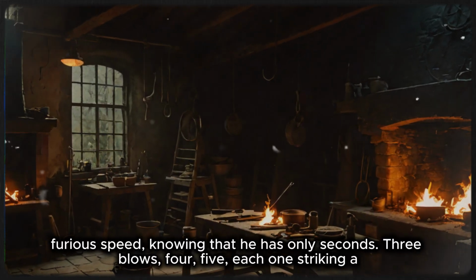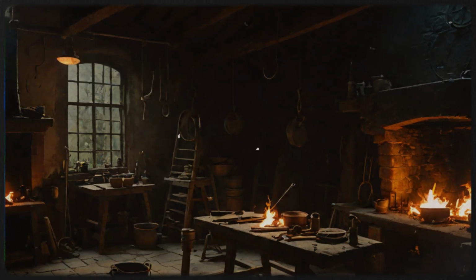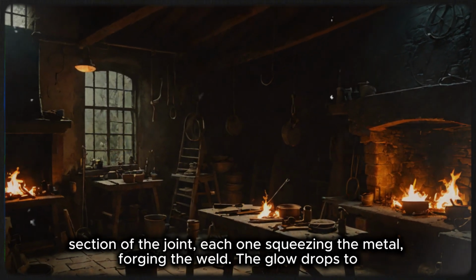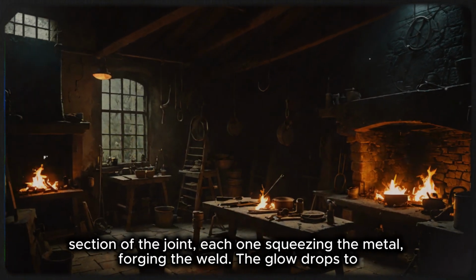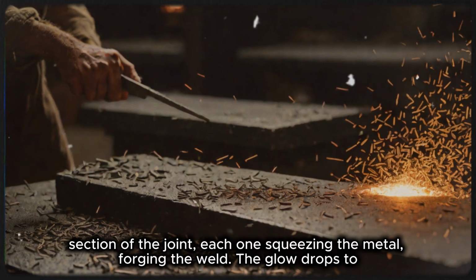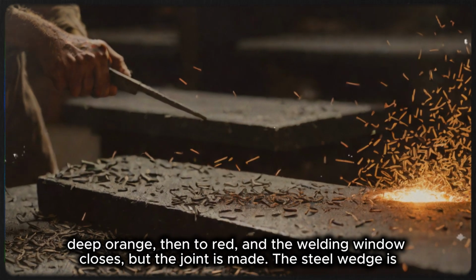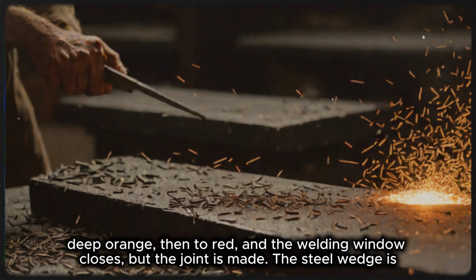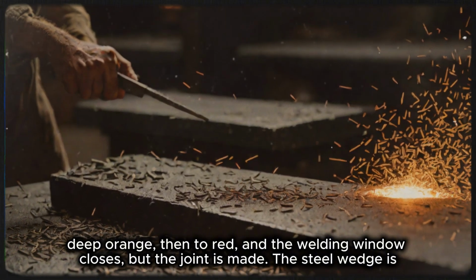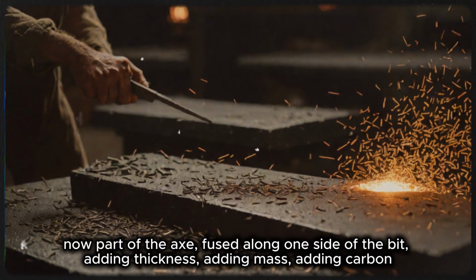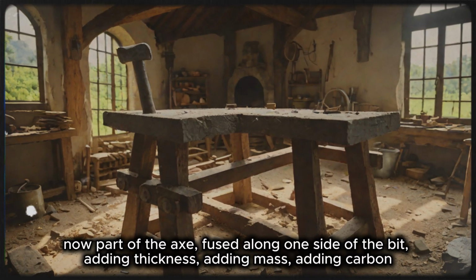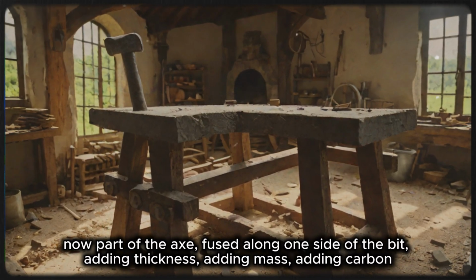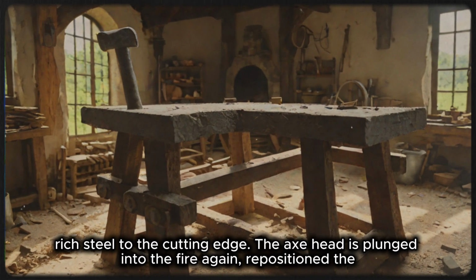3 blows, 4, 5, each one striking a different section of the joint, each one squeezing the metal, forging the weld. The glow drops to deep orange, then to red, and the welding window closes. But the joint is made. The steel wedge is now part of the axe, fused along one side of the bit, adding thickness, adding mass, adding carbon-rich steel to the cutting edge.